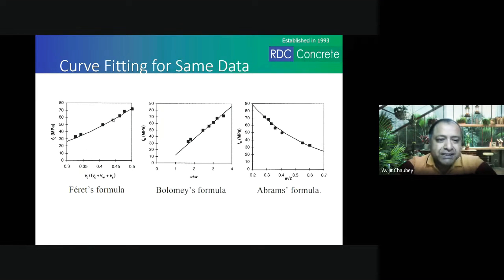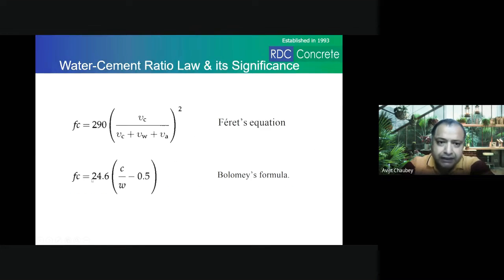And what he did was he plotted the equation as per the Feret's formula, as per the Bolomey's formula, and as per the Abrams formula for the same set of water cement ratio or same set of mixes and their strength. And if you see, all these equations actually fit the curve very well. The only thing that he did was, if you see, he changed these numbers. So to fit this equation as per his data, he only changed these numbers. And this was how he did the curve fitting.